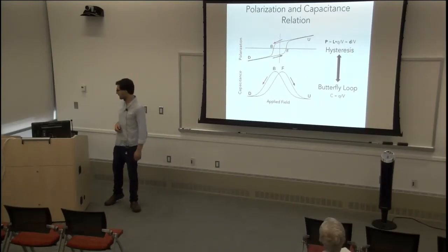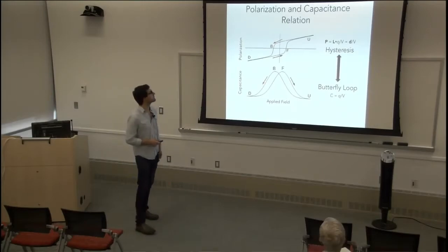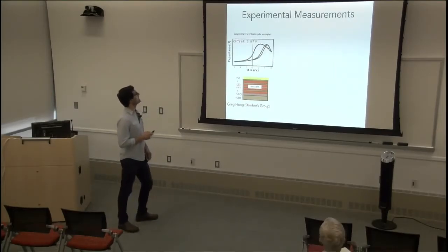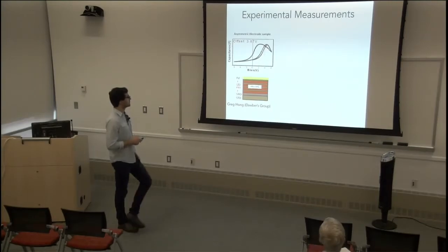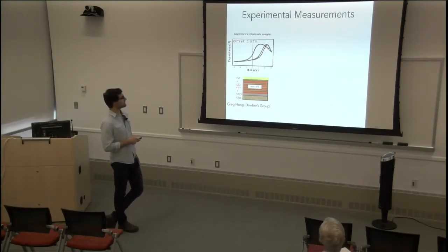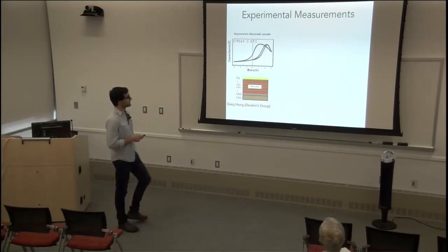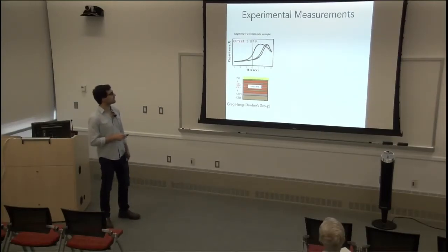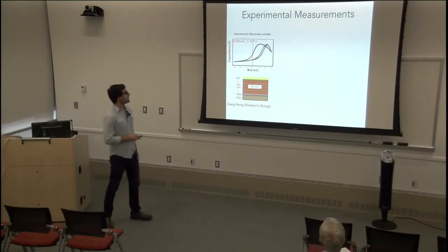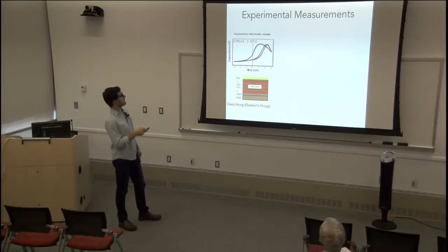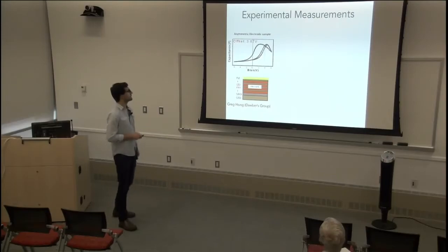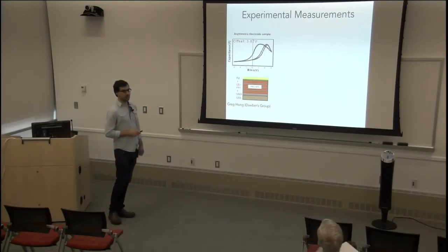So with that, let's start talking about experimental measurements, with an example. Here I have a strontium titanate, lead titanate superlattice for a given thickness. Here it happens to be 7 lead titanate unit cells and 1 unit cell of strontium titanate. And this is your butterfly loop. One thing you notice right away, maybe about its weird shape, is that the center, which is where the two curves cross, is offset from 0. It's offset by about 4 volts.